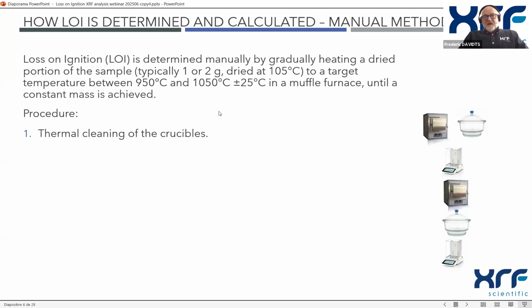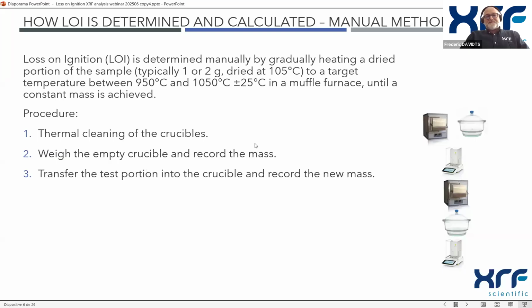This process is relatively long because there are a lot of steps. First we need to do a thermal cleaning of the crucibles in the furnace, and then after we need to cool in a desiccator, then weigh the crucible and record the mass, then transfer the sample into the crucible and again record the mass. Then we transfer as fast as possible the crucible inside the furnace for the LOI determination during an hour and a half, 2 hours, depending on the product.